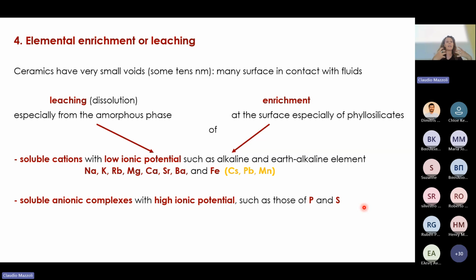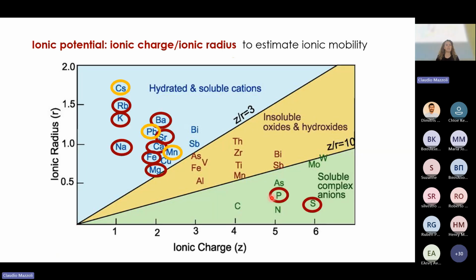Okay? So there are some chemical elements which, let's say, can easily be removed from a ceramic material because they form soluble cations, because they have a low ionic potential. And here there are some of them: sodium, potassium, rubidium, magnesium, calcium, strontium, barium, iron, but also some trace elements like cesium, lead, and manganese. Right. So if you want to see this, considering the ionic potential, these elements are those that normally represent hydrated and soluble cations, or soluble complex ions, okay, like the phosphorus and sulfurs. So other elements like titanium, zirconium are much more stable.